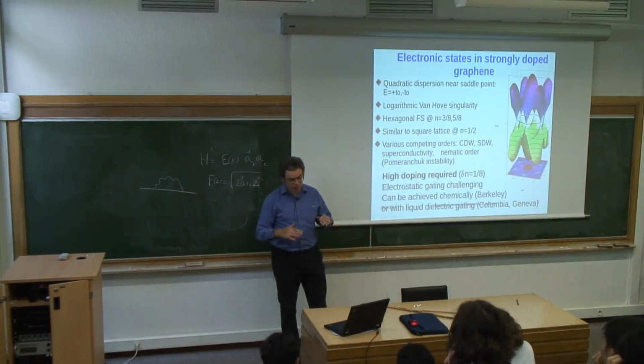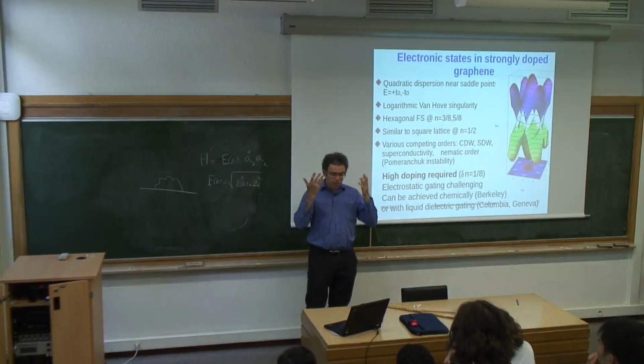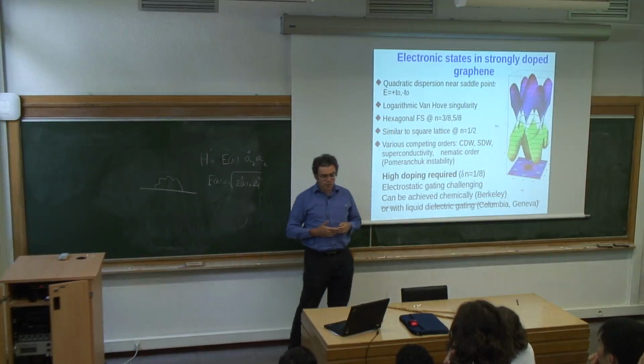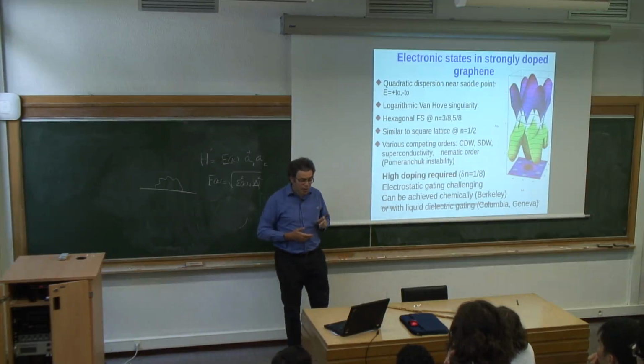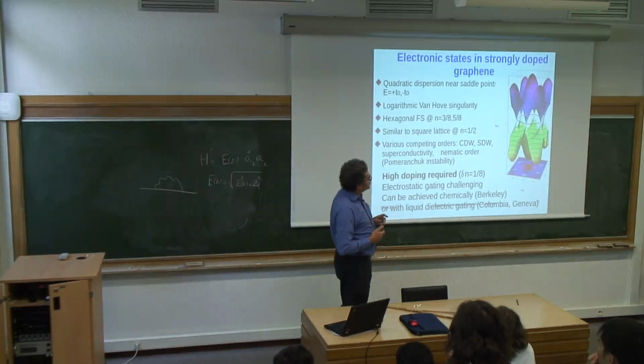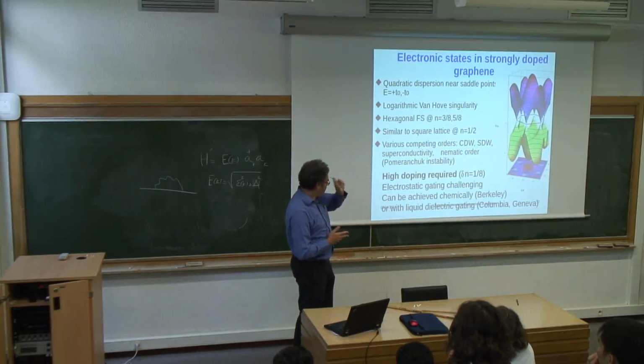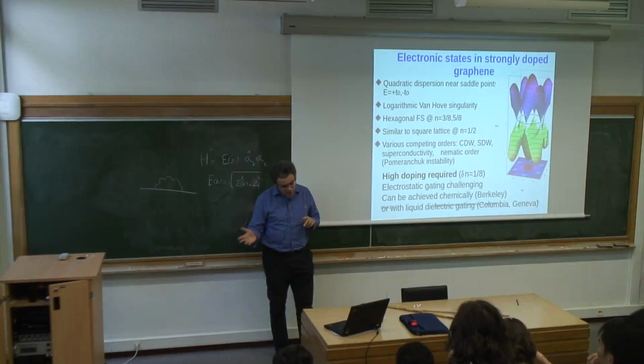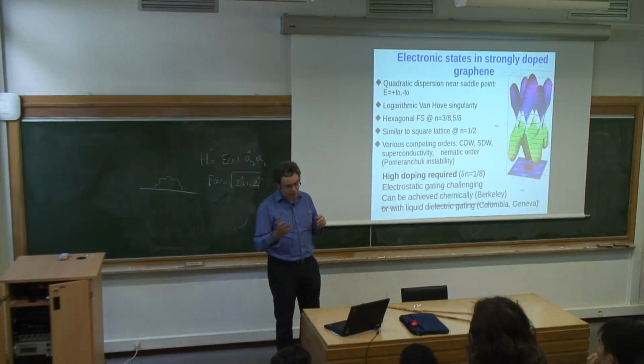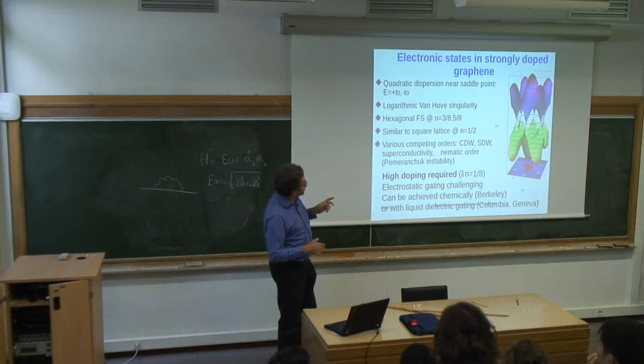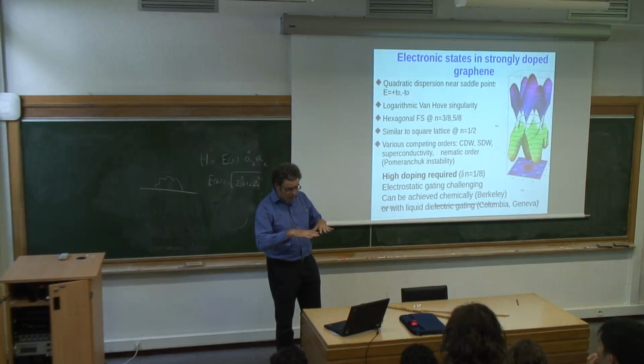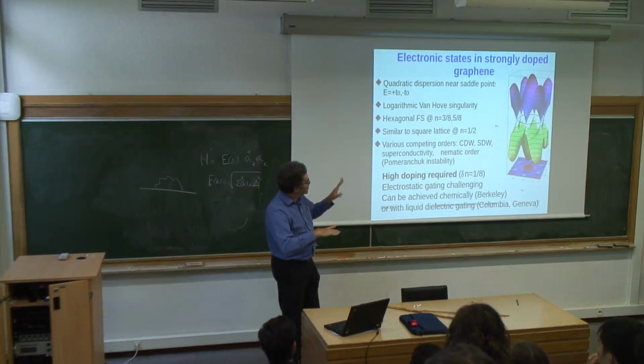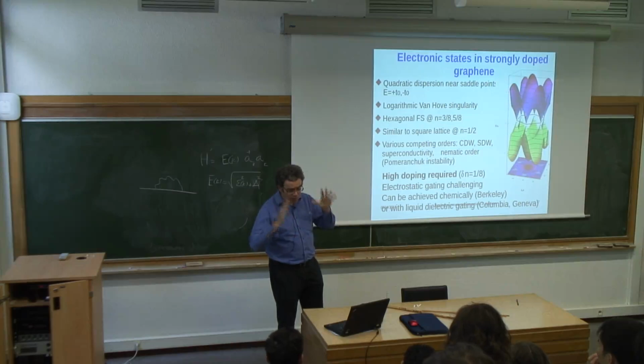proposed a long time ago that if you have a saddle point and you dope the material to the saddle point, because your density of states goes high, your superconductivity will be enhanced because density of states appears in the exponent, right? That is totally true. However, in systems with saddle points, you often get competition between superconductivity and other types of order, spin density wave and charge density wave. The reason is that in crystal structures saddle points typically come in pairs or in triplets, and so they are nested, like in the simplest square lattice Bloch band structure, where there's a diamond-shaped Fermi surface at half filling. Then you have two saddle points, and they are nested.